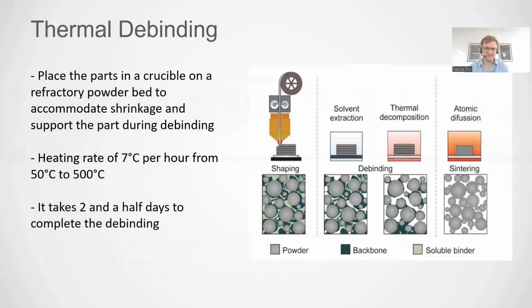Once you've made this chemical debinding, you put your part in the furnace, and what happens is that you burn away the binder. To do that, you really need to go relatively slowly during the heating ramp. So we say between 7 and 10 degrees Celsius per hour. Depending on the part, it could be quicker, but we usually advise to be really slow in that stage, which makes the thermal debinding the longer step in all of the process. And then we directly do thermal debinding and sintering in the same furnace, which saves some time and cost.